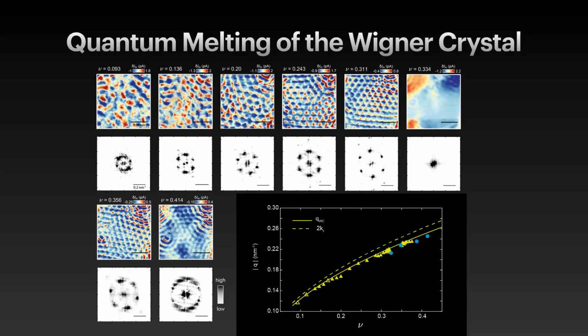So why do you have no feature in the thing on the right-hand side of the block? This one, the point is that this is inside the incompressible state, so the experiment may be compromised. The liquid is incompressible, but you're just at the edges of the plateau where you can add quasi-particles. The gap is kind of collapsed, but you still have a quantized Hall conductance then.